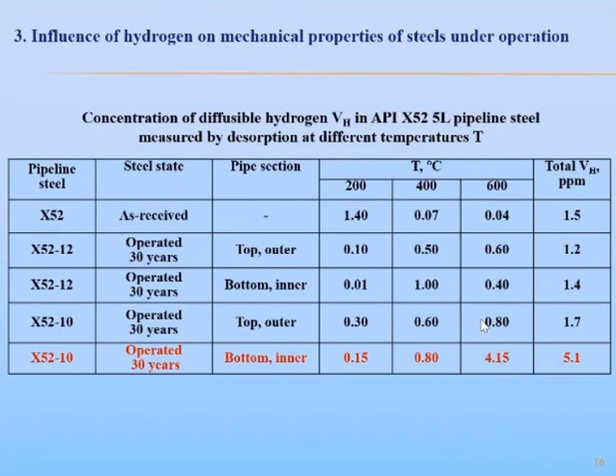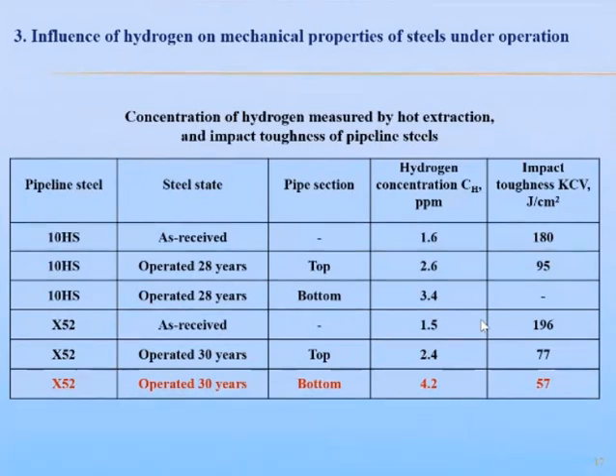It's important to emphasize that it's not really the hydrogen concentration that causes embrittlement, but rather hydrogen diffusivity through the steel. As you can see on this slide, a decrease in brittle fracture resistance is in good agreement with hydrogen concentration in metal. Higher hydrogen concentration corresponds to a lower level of impact toughness.